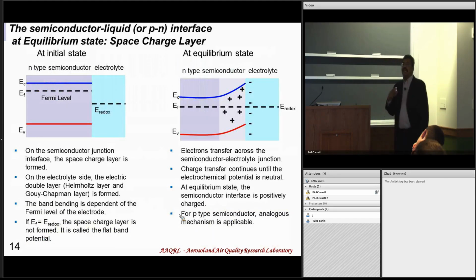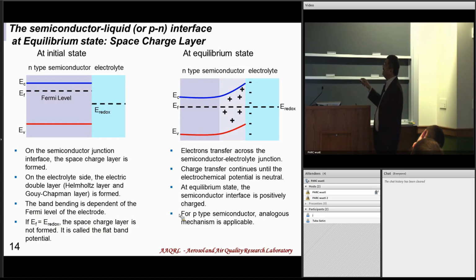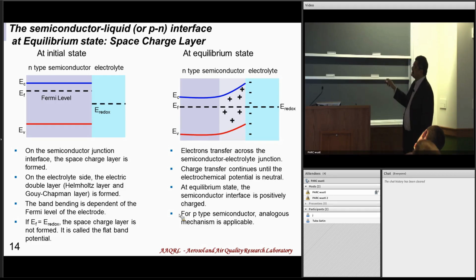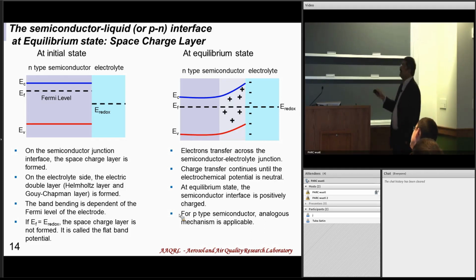And then the space charge layer, the concept of the space charge layer. So if you look at all these band and energy levels, and here I just show a certain redox potential, and because of this band bending that takes place at equilibrium, you want the Fermi level to become equal to the redox levels, and because of that there is a certain band bending, and this is very important because this region is where the electrons and holes or the positive charges would separate, and that's what I want.